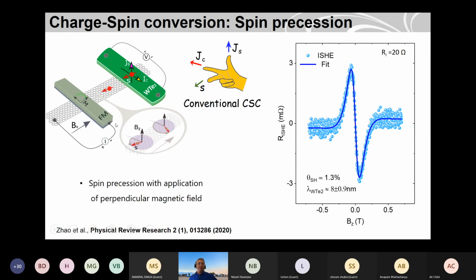Here I show one experiment where we send a spin current from the ferromagnet into the graphene. Then spins have to enter the tungsten telluride and we measure a voltage. It's a non-local measurement, so only spins entering there will affect the measurement. While spins are going, you will see a voltage signal which will change if you change the magnetization of this magnet. But we did an experiment with spin precession, as I told you earlier. Spins will precess, and that will modulate the signal like this. From this measurement, we can know the direction of the spin polarization while they are entering the tungsten telluride.